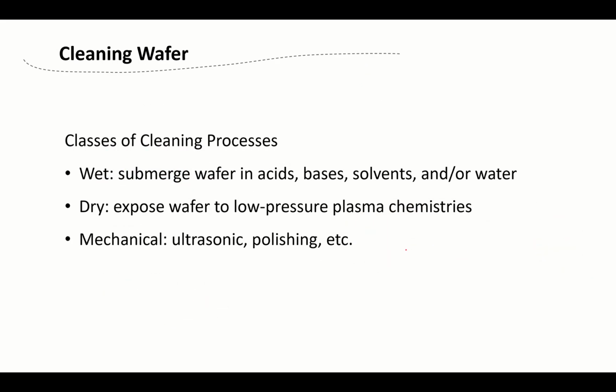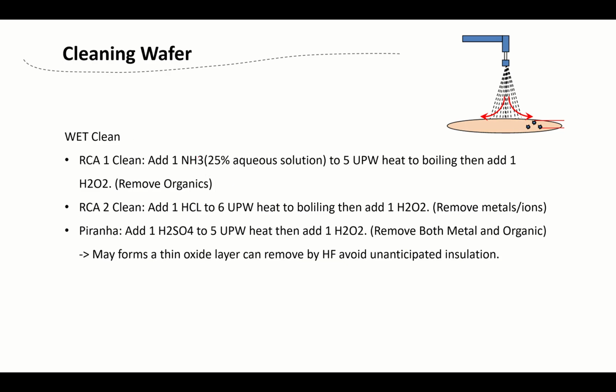In general, we will use three kinds of ways to clean the wafers. First is wet cleaning, in which we submerge the wafer in an acid bath. Second is dry etch, where mostly we use plasma to do etching. Third is mechanical, where we use ultrasonic to do the cleaning. For wet cleaning, we can use RCA1, which is ammonia with peroxide to remove organics, or hydrochloric acid with peroxide to remove metals and ions, or piranha solution, which is sulfuric acid with peroxide to remove both metal and organics.